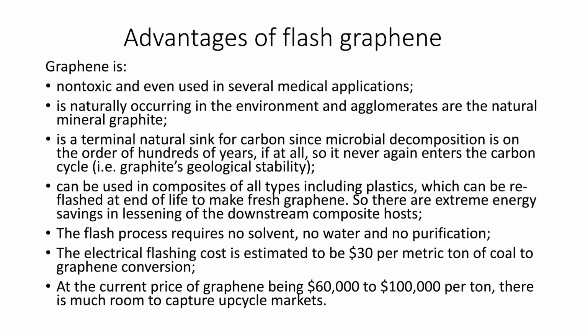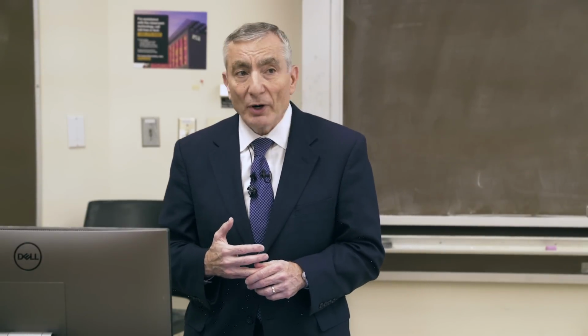It can be used in composites of all types. The flash process requires no solvent, no water, and no purification. If you have silicon in there, if you have aluminum in there, those are distilling out. Silicon and aluminum are both boiling at about 2600 centigrade. This is going to over 3000 centigrade. Carbon doesn't boil out to almost 4000 centigrade. So you have a big window there, and all these other elements can come subliming out or boiling out.